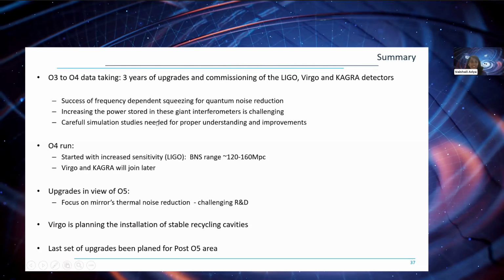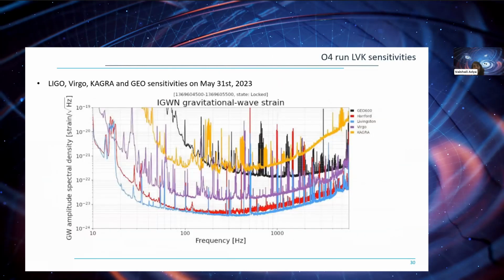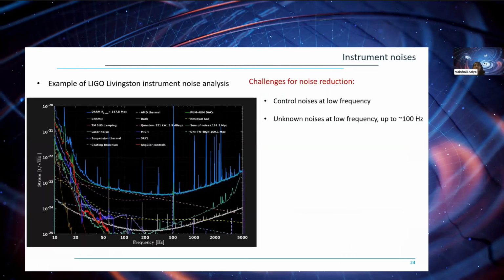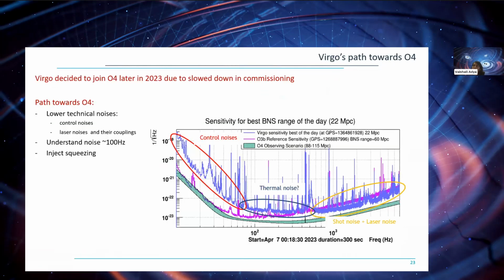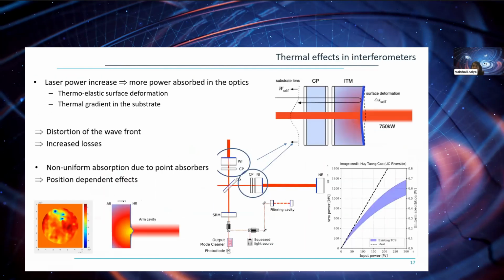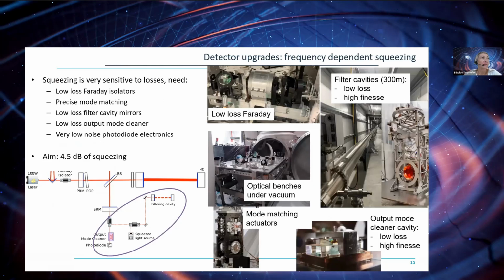Maybe, since I have the privilege of chairing, I can ask you a very quick question. Since you very rightly mentioned that loss is very important for squeezing, do you have an estimate off the top of your head of how much the loss was decreased between O3 and now? The loss in the squeezing path. Yes, I think that in O3 it was about 30 to 40%, and now we have reached about 15%. So it was decreased by more than a factor 2.